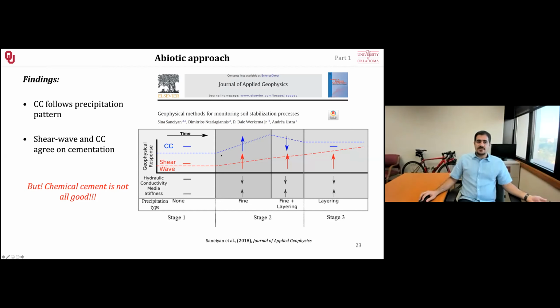Initially, as I said, we assumed that we have a powder precipitation increase in the complex conductivity magnitude signal, and then these coagulated and created layers of calcite on top of each other, so that initial surface area that was because of the powder is reduced now. And then we reach a constant level because of this equilibrium going on.